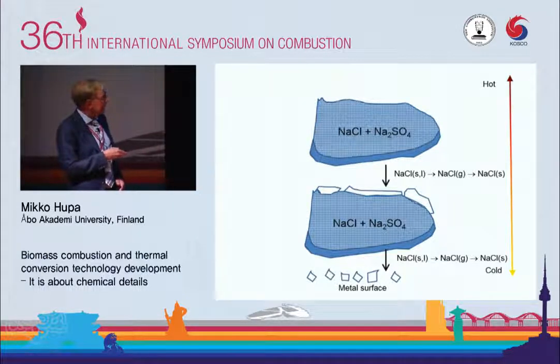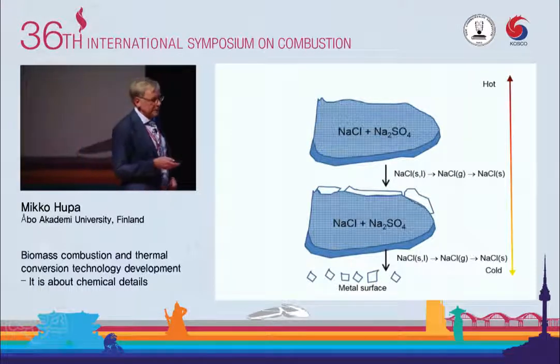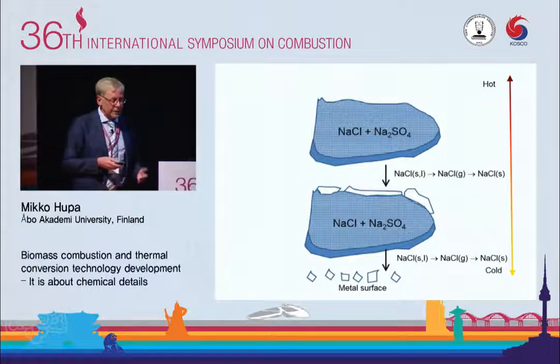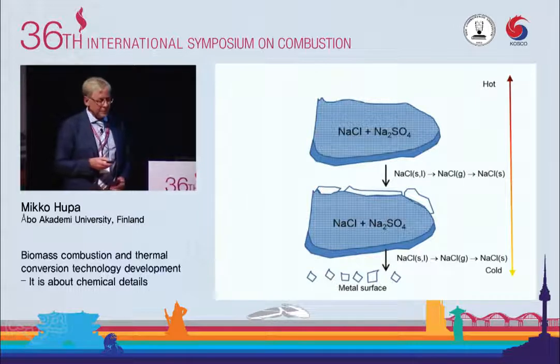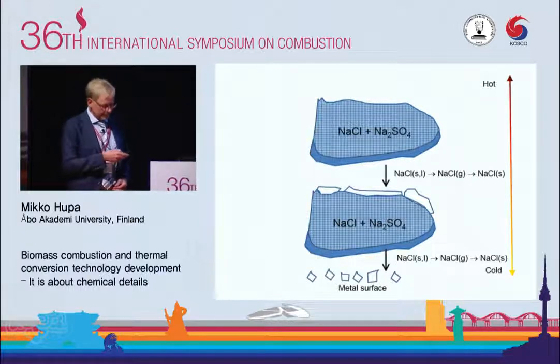And the consequence of this is that this chloride will partly go all the way to the steel surface, depending on the temperature conditions, and can enrich high amounts of this, even from small amounts of chloride. So this is something we want to study more.